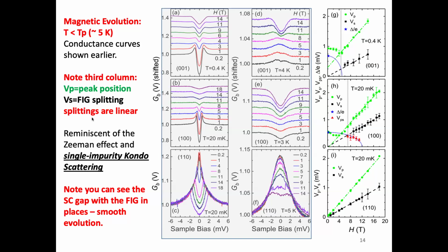What we see here is this precursor and this field dependence. This is an argument why we think it's preformed pairs, because we only see this field dependence if there are either preformed pairs or Cooper pairs. I don't think it's proved that it's preformed pairs, but it's interesting that you only see this linear field dependence of the splitting in the pseudogap phase and the superconducting phase.